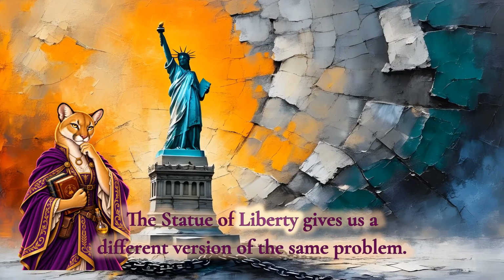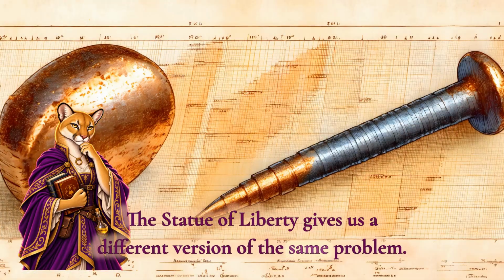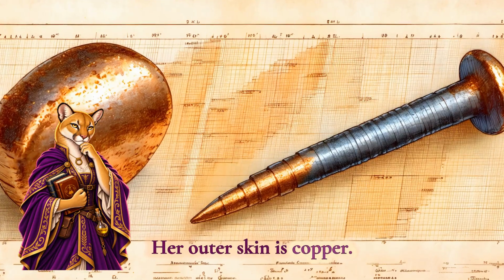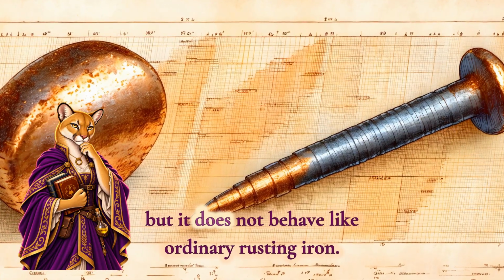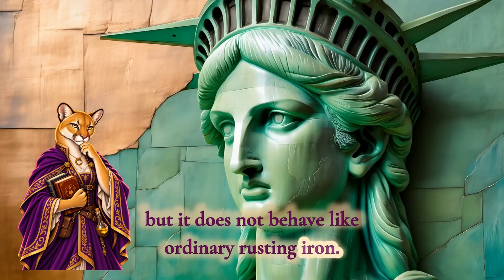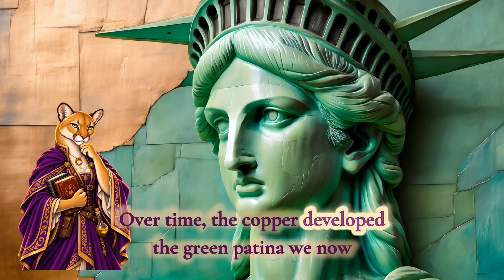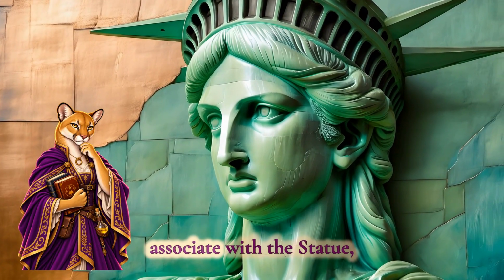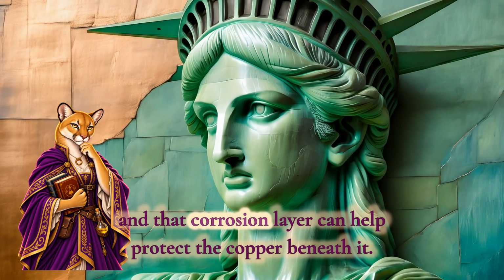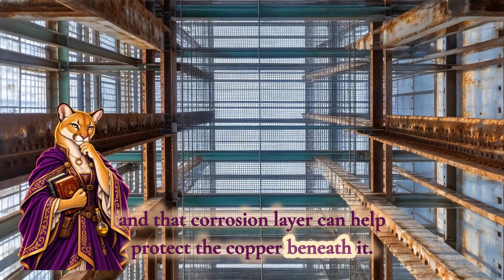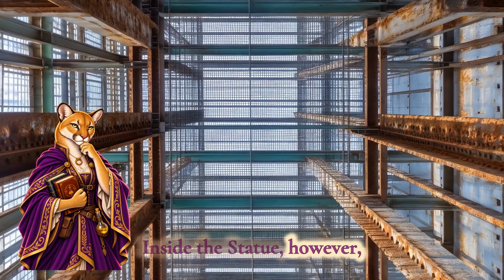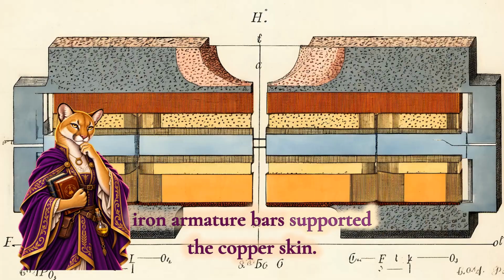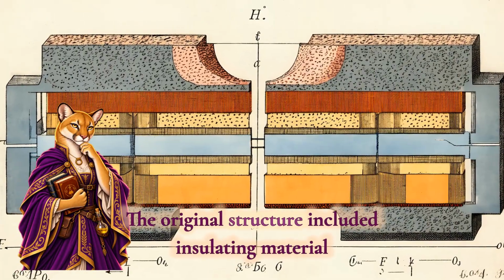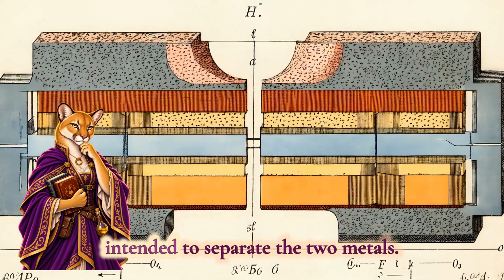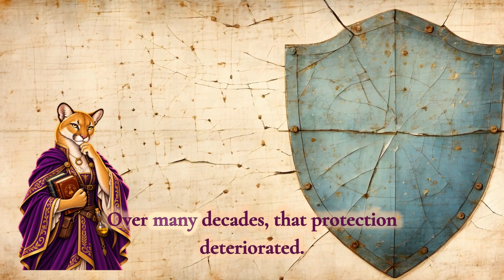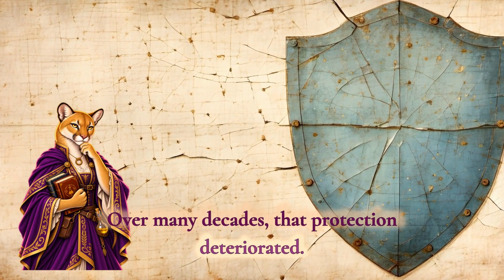The Statue of Liberty gives us a different version of the same problem. Her outer skin is copper. Copper corrodes, but it does not behave like ordinary rusting iron. Over time, the copper developed the green patina we now associate with the statue, and that corrosion layer can help protect the copper beneath it. Inside the statue, however, iron armature bars supported the copper skin. The original structure included insulating material intended to separate the two metals. Over many decades, that protection deteriorated.